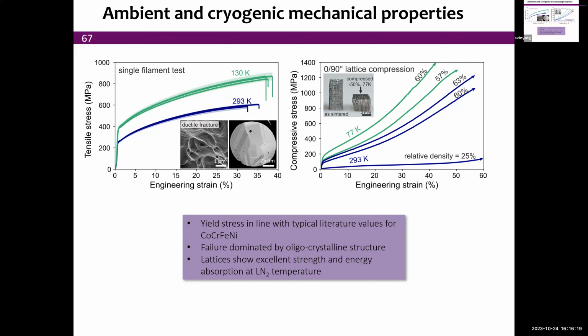Now, this is for the filament. Once we make a lattice, shown here, we of course get much lower strength, but also excellent, and this is in compression, I should say, so the ductility is maybe less impressive than in tension, but you see the effect of temperature on the strain hardening, as well as the yield stress, and of course, still very, very good ductility in the material, and so energy absorption capability at cryogenic temperatures.